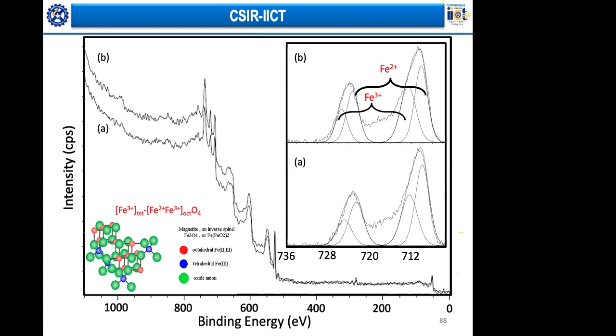When such a thing is examined by XPS, detection of iron is one. This is what is called a survey scan, and these peaks around 700 electron volts are due to the iron which is there. When we look at these high resolution narrow scans, because iron is in 2 different oxidation states, we get 2 different peaks, one due to Fe2+ and the other due to Fe3+. This is the fresh catalyst and the used catalyst, and in both cases you can see that the ratio of Fe2+ and Fe3+ remains the same. This is one of the very few techniques which gives us information about the metals, their oxidation state, and their molecular environment.